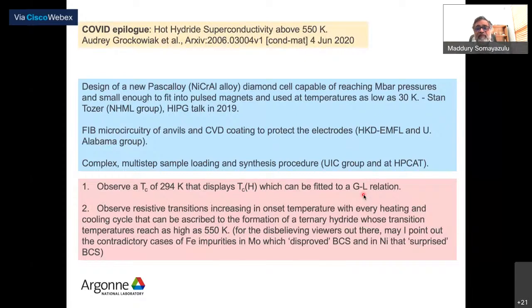Now, the question we have is, what is actually driving this? I mean, we started with a simple lanthanum hydride system. In fact, that paper is this paper. And now we're beginning to see that there are things happening in the system which are driving the transition temperature higher and higher. Just as in the carbon sulfur hydrogen system, where you started with a very low transition temperature of about 30 Kelvin and drove it higher and higher with increasing pressure, you are able to drive the transition temperature higher in this lanthanum hydrogen system by just cycling it with temperature, and it seems to be going up.